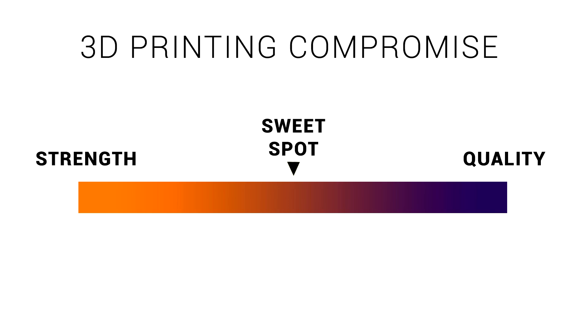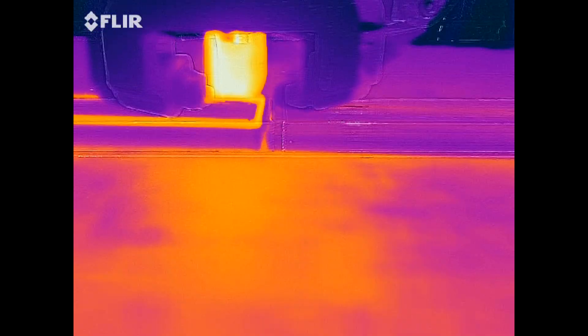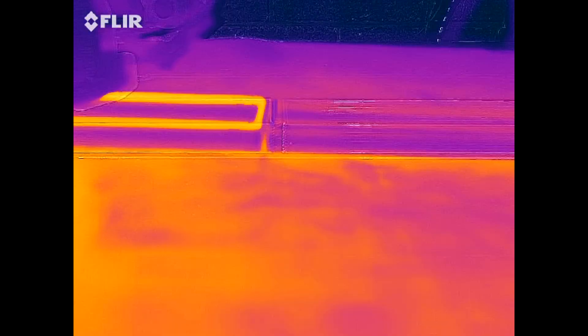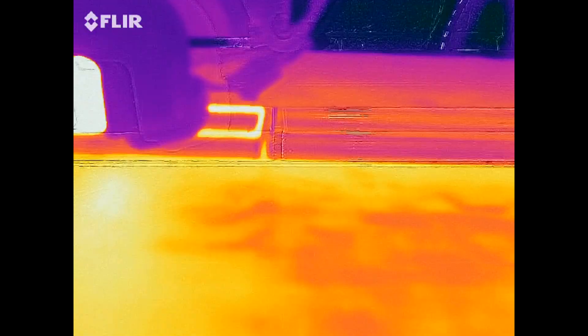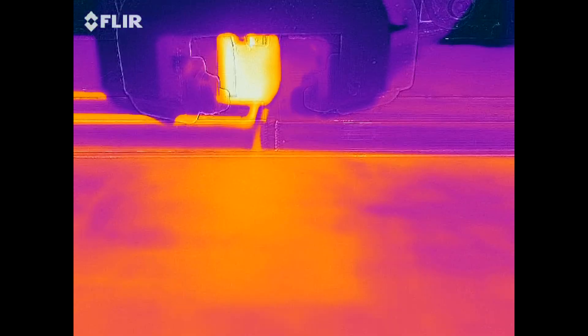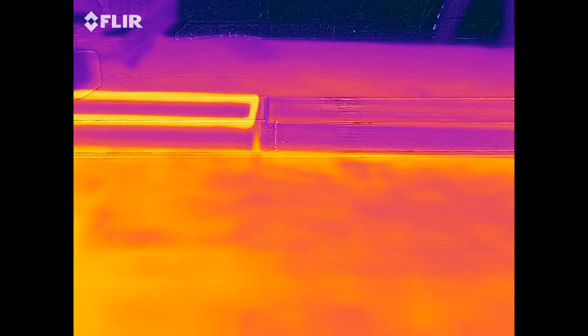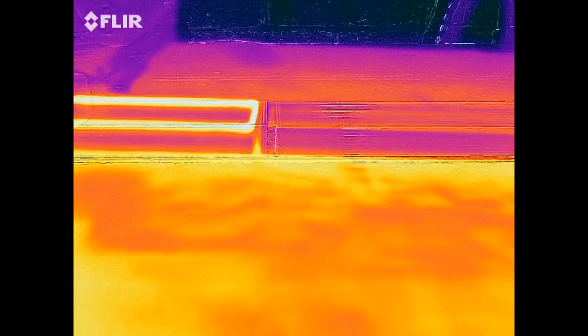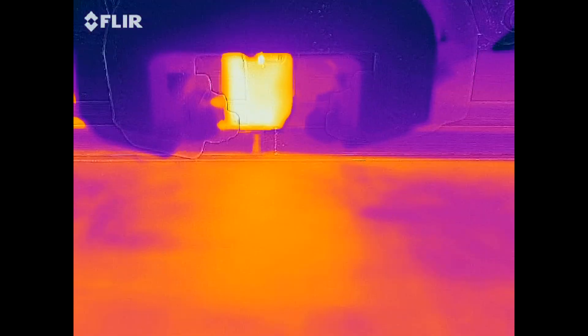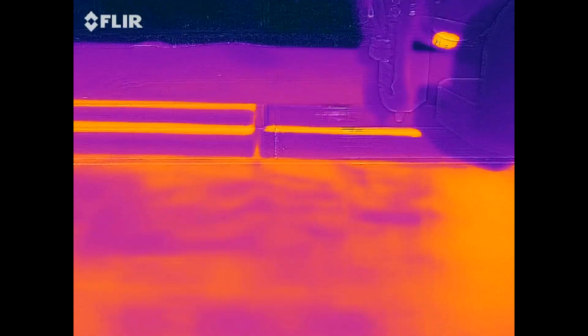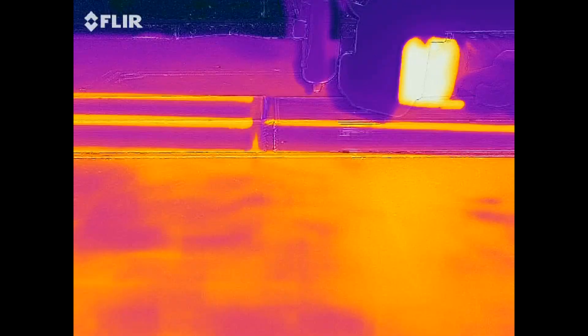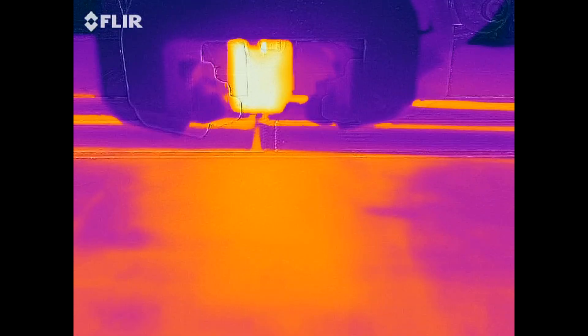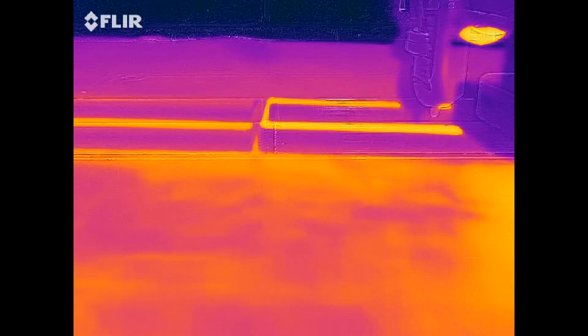So what settings can we tweak to find that sweet spot between strength and quality? There's actually quite a few, but I think the best thing for your buck will come from hot end temperature, part cooling, and feed rate. As filament is extruded, it's quickly cooled by the part cooling fan, and then it only takes a few seconds before it cools down closer to ambient temperatures. We can see the section on the right has completely cooled by the time the nozzle returns to it for the next layer. So to maximise interlayer strength, we can increase the hot end temperature, decrease the part cooling, and slow down the feed rate, to give the new layer of plastic the best chance at bonding strongly.